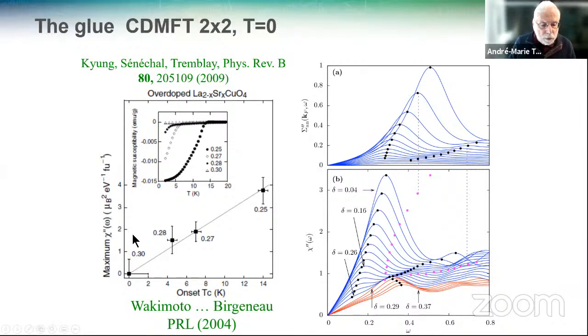And if we look at the overdoped region, these are experimental results for where the maximum of chi double prime is as a function of onset temperature, which is here a measure of doping in some sense. I mean, doping is here. We are in the overdoped region. You see that the maximum goes down in frequency. This is a frequency scale. This is the location in frequency of the maximum. And you see that's what happens here.